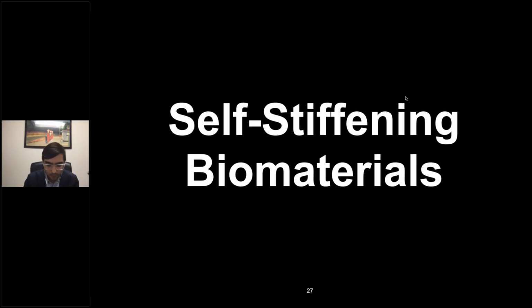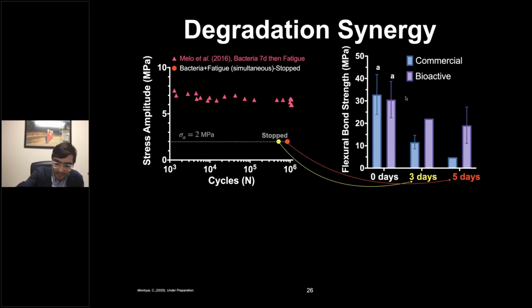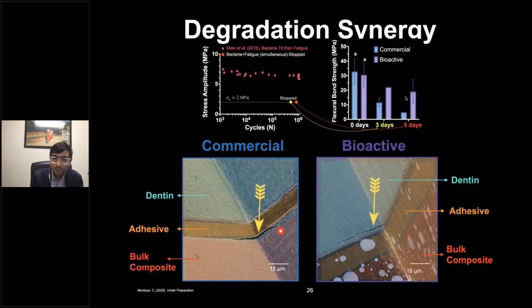Now let's move quickly to the self-stiffening biomaterials. One of the challenges of having materials of this type of bond is that the mechanical properties, the Young's modulus of all these materials, are different. Dentin, the modulus can be 20. The modulus of the adhesive is around 4 to 5 gigapascals, and the modulus of the bulk composite is around 10. So there's a big mismatch of the modulus of those 3 materials, and that can also influence stress concentration happening at that bonded interface.